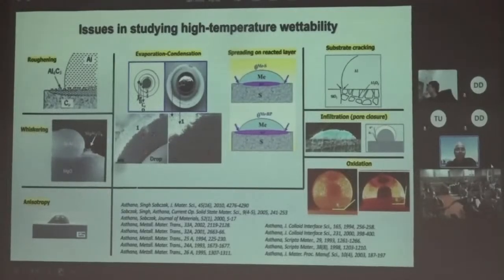So here is an example of a nickel droplet that was in contact with a single crystal alumina with a chromium PVD layer. And what we see here is that even before the droplet can spread completely, there is evaporation and condensation of nickel and formation of different zones of nickel chromium eutectic. So the droplet is actually spreading on a modified surface.